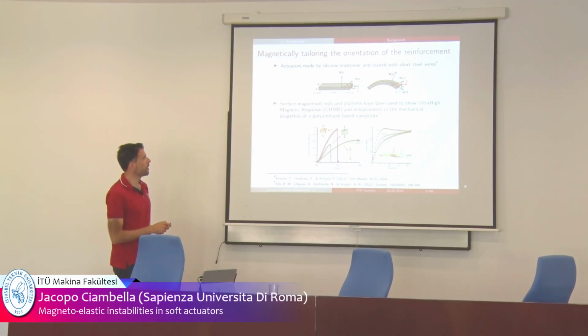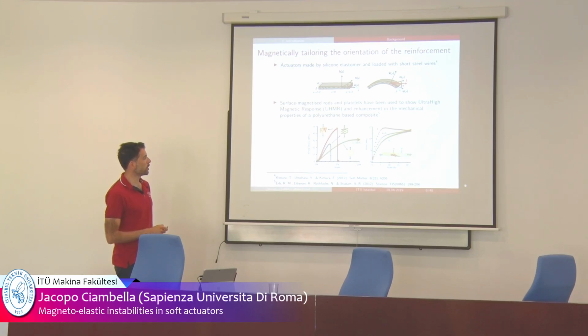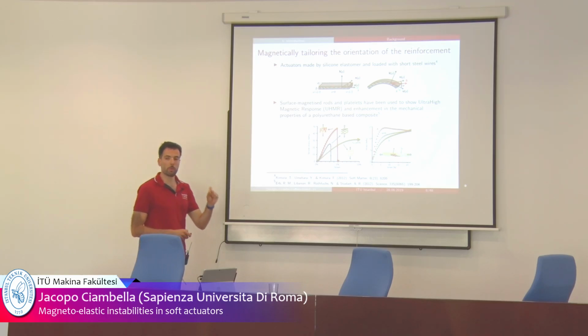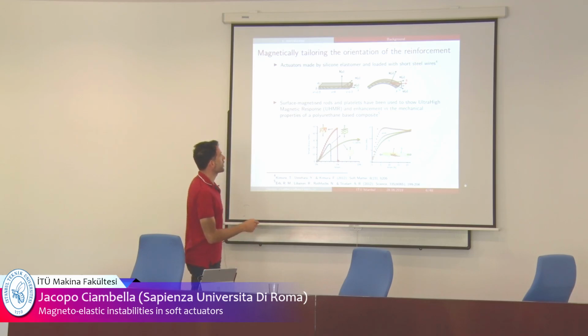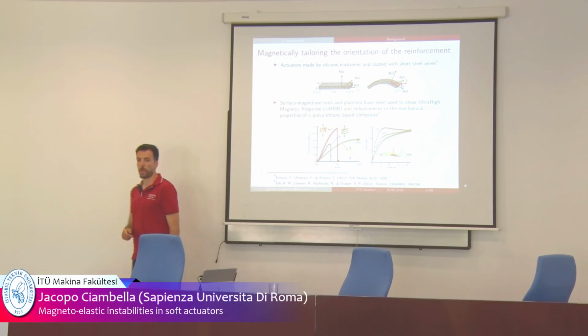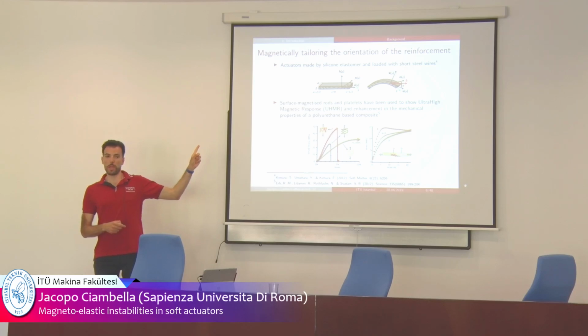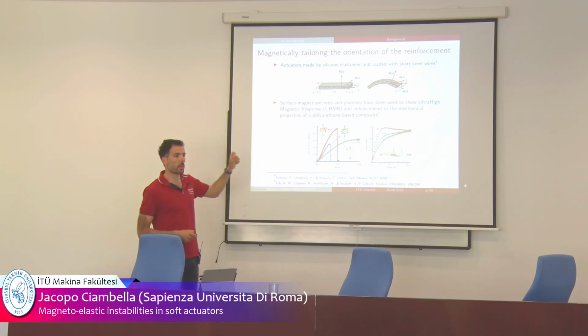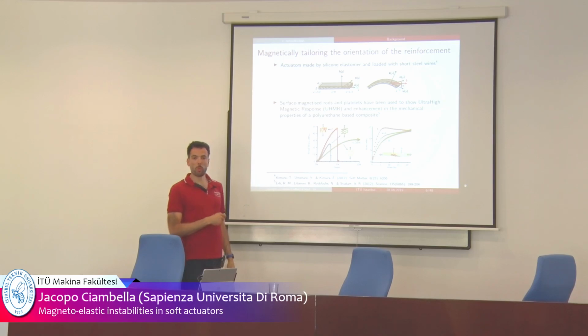Then something very similar to what I will show you has been carried out by Kimura group, and I think they use silicone rubber reinforced with steel rods. Okay, and what they obtained, they started with this very nice distribution of the steel rods. They apply a magnetic field, and they ended up having this deformed configuration here. Okay, and I will tell you more about this later on, because this is exactly the same physical mechanism that I will exploit in this presentation.